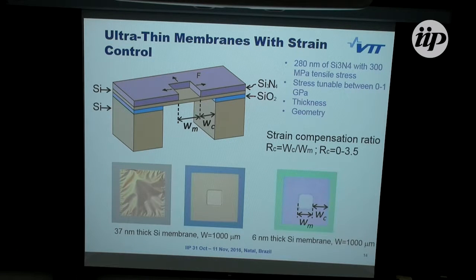Then of course thickness: the thicker this is, the stronger the force. And then the third one is the geometry. We can change this overlapping part which goes on the membrane, say this ratio to this window ratio, and this is also something we can use to control the strain. And this works very well, so we can make samples with down to 5 or 6 nanometer thick membranes, and this is 1 millimeter by 1 millimeter. So these are extremely robust materials.